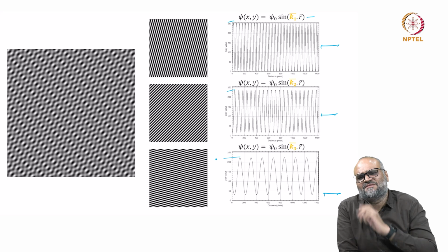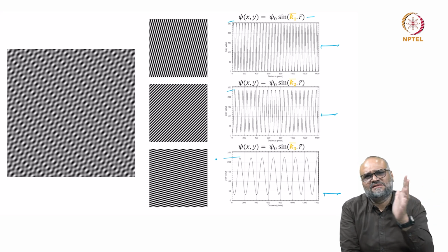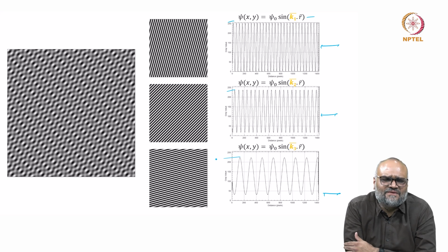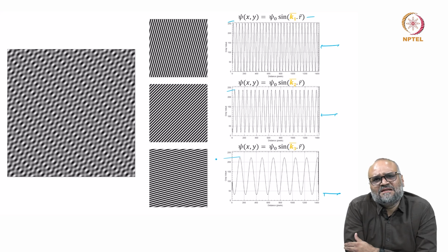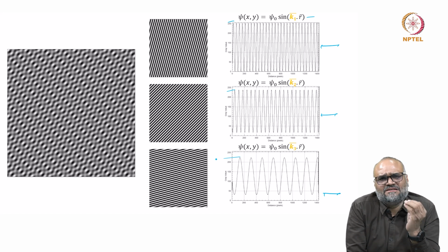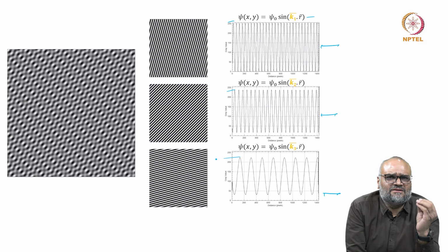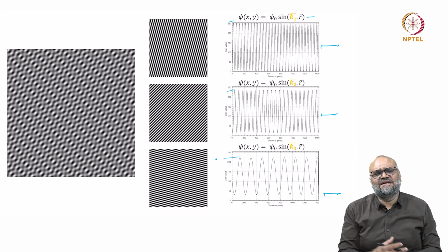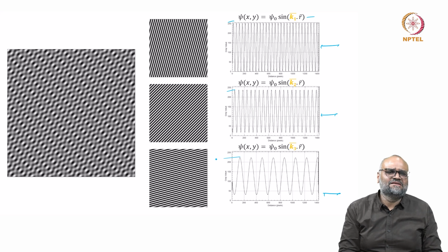With or without a specimen, when an electron beam is simply propagating through a magnetic lens, bear in mind that there is always a phase shift happening. And by understanding these phase shifts and by understanding how the specimen can be represented with some kind of an electrostatic or a magnetic potential, we can understand and model how an image is formed within an electron microscope. And there are different imaging modes, and we see different information that can be obtained from different imaging modes. And this is what is happening within an electron microscope.